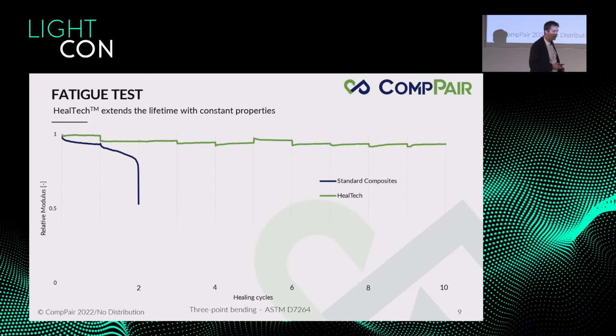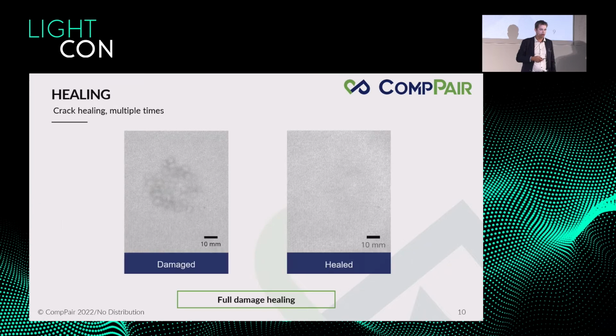What we can do is exactly the same for fatigue testing, where we came on the part and we really cycled many times, actually 20,000 in this case. And what you see is that we've done that for HealTech, and each of the vertical lines is one healing cycle. So with our composites, each time we regenerate, we can start again, whereas for standard composites, for the same layup, and this was a standard thermoset-based composite, you see that the damage continues and then the part breaks.